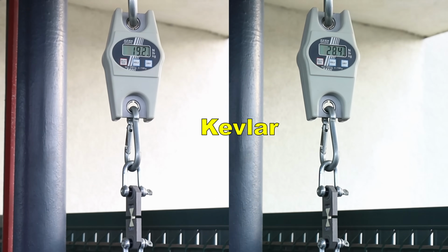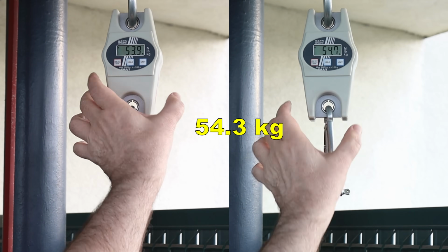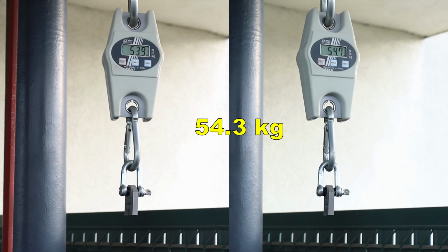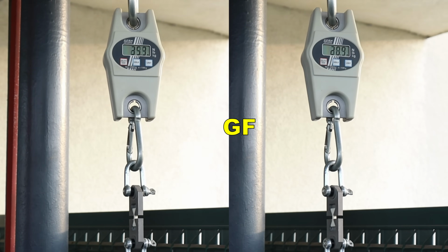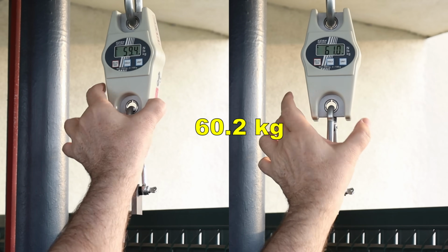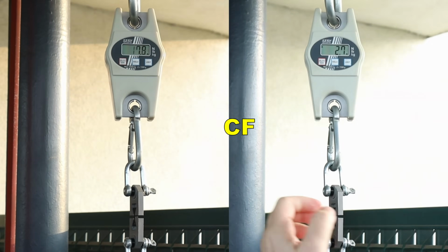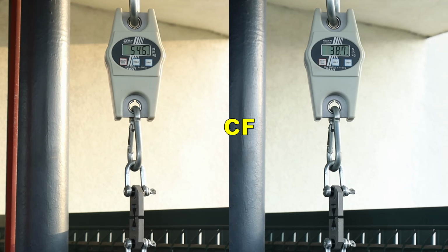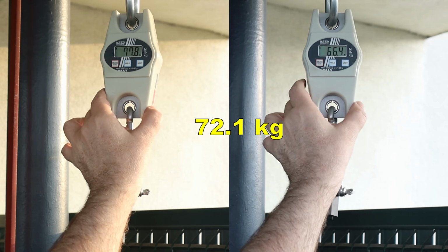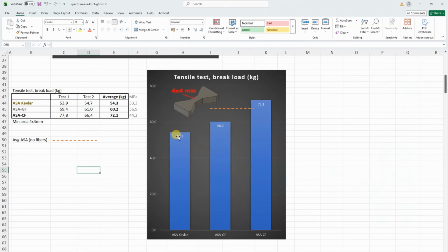Tensile test, this is Kevlar. These are horizontally printed objects. Glass fiber version. Stronger a little bit. And carbon fiber version. The strongest from these three. And here you can see the numbers on the graph. And with this line I marked the average ASA without any fibers. And we can see the CF is a little bit above it and the other two below this line.